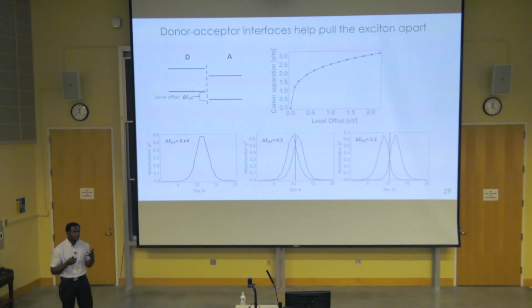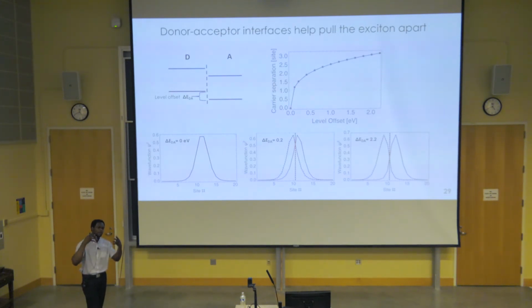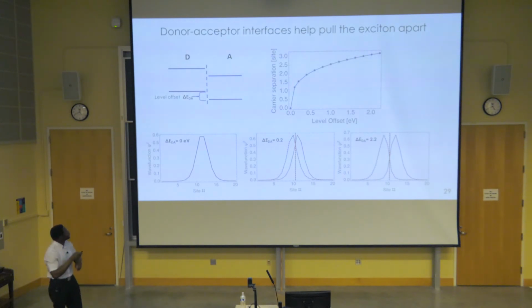So next we look at what happens when the exciton is at a donor-acceptor interface. Here we look particularly at the effect of the energy offset, that is the difference in energy between the highest occupied molecular orbitals on the two sides of the interface, the donor and the acceptor side. As this level offset is increased, we observe that the separation distance between the charge carriers also increases, as you have evidence here in this plot of the probability distribution of the two carriers. As we increase the energy level offset, we can see that the two carriers are pulled apart.